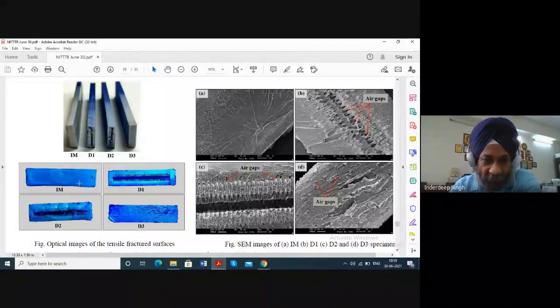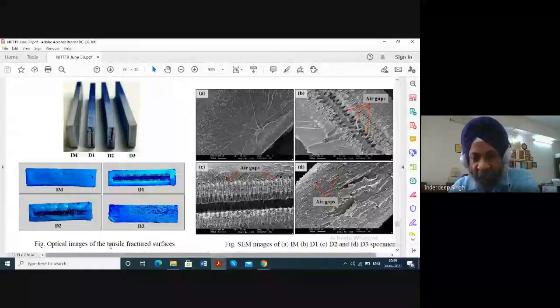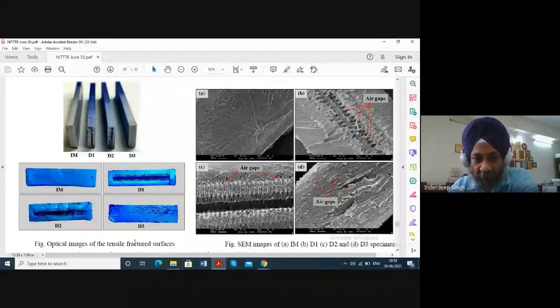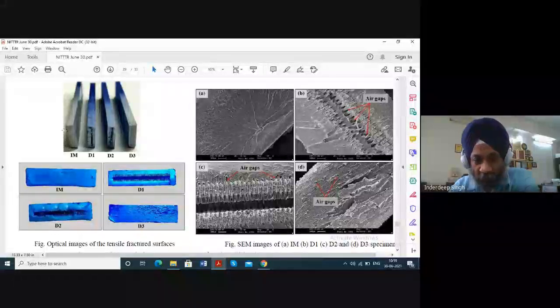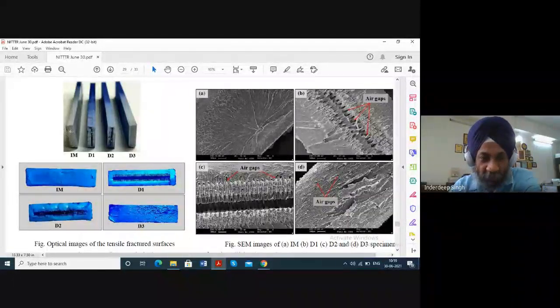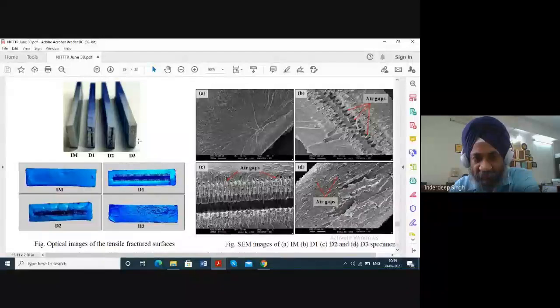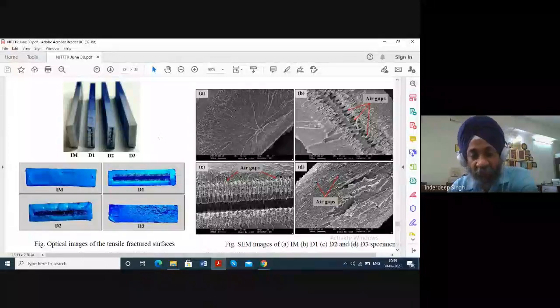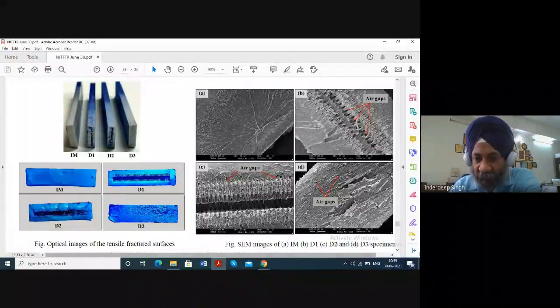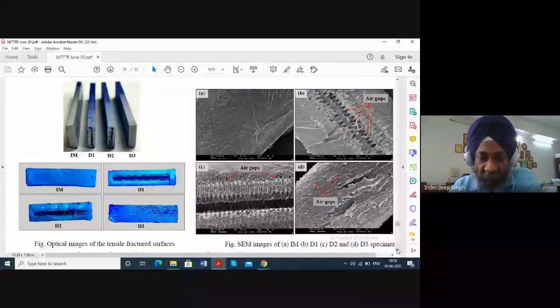And here you can see the cross section areas, optical images of the tensile fractured samples. We can see here IM is a completely rectangular cross section, filled cross section, and similar is the case with D3, 100% fill density, whereas in D1 and D2 we can see there are hollow sections inside. So optical images of the tensile fractured samples you can see here on your screen.